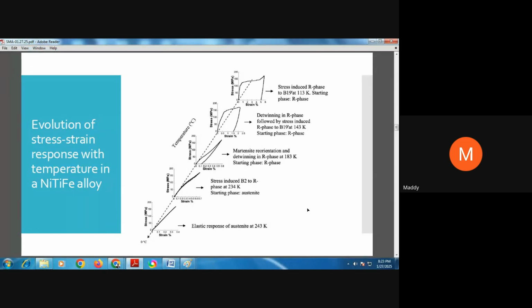But as you lower the temperature, you are actually transitioning into the intermediate R phase. And when you apply stress, you can see that you are able to recover around 0.7% of strain, which is significantly higher than conventional materials. And this is because of the stress-induced austenite to R phase transformation.